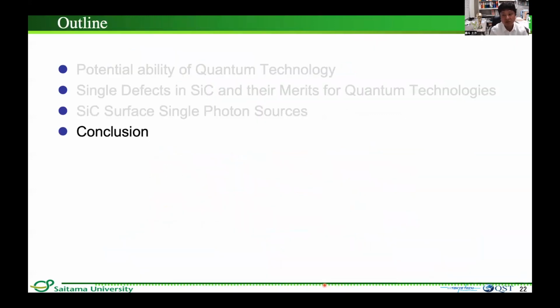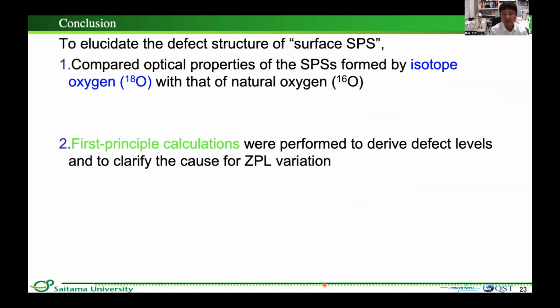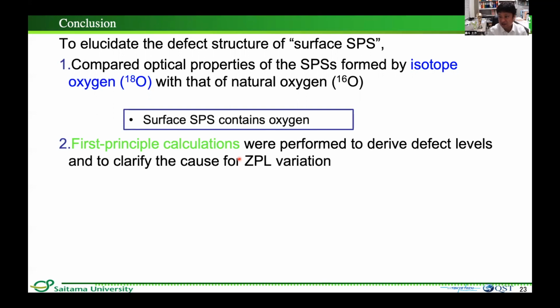Finally, I would like to conclude my talk. These are my conclusions. To elucidate the defect structure of surface SPS, we compared optical properties of the surface SPS formed by isotope oxygen, 18 oxygen, with that of natural oxygen. Also, we performed the first principle calculation to derive defect levels and to clarify the cause for ZPL variation. According to isotope oxygen measurements, we found that the defects originating surface SPS contain oxygen.